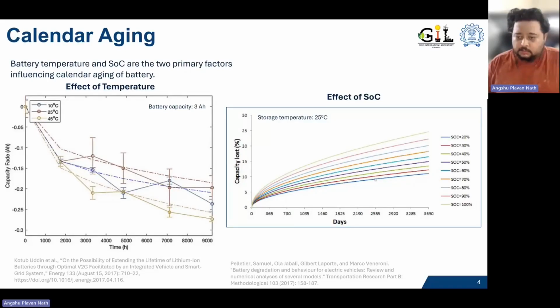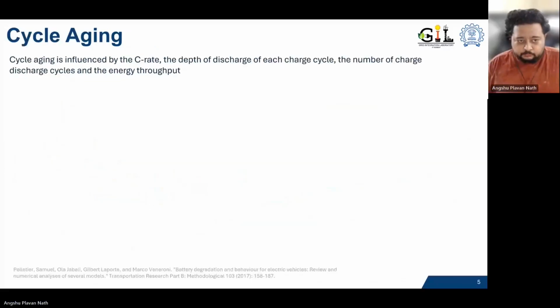Again, this was an experimental study where different samples of the same battery were stored at different SOCs, with the storage temperature kept constant. So as we can see, calendar aging is impacted both by your storage SOC and by the temperature at which it is being stored.